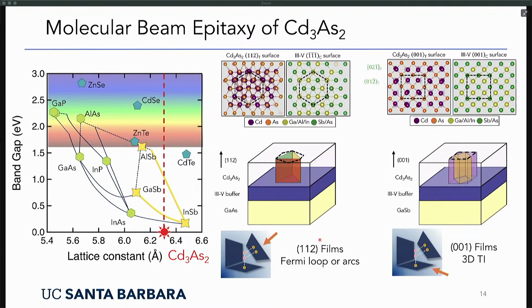The other difficulty is that cadmium arsenide likes to grow in a 112 plane. That's the low energetic growth plane. The equivalent in a cubic structure is the 111 plane. That's not a common growth orientation for 3-5 semiconductors, so we had to develop the growth of 111 oriented 3-5 semiconductors. There's not all that much in the literature about that, in order to get a suitable growth surface for the easy growth direction for cadmium arsenide. Later we also developed 001 growth of cadmium arsenide on 001 surfaces. That's a lot more difficult, and it doesn't grow quite as well as the 112 direction. On the other hand, the 3-5 layers grow better in this orientation.